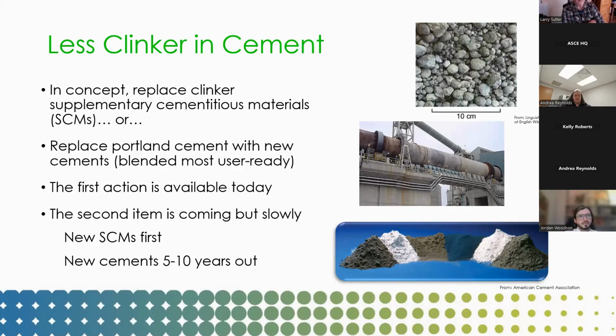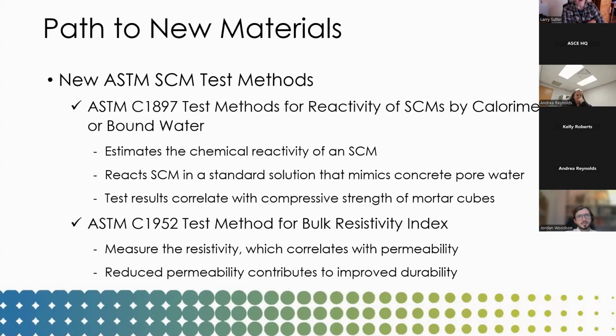Next slide. So how do we get there? Well, the first thing we got to do is look at new tests that are going to help provide us information we need. And so we do have a couple new tests. We've developed C1897 for measuring the reactivity of SCMs by calorimetry or bound water. And this is a completely new approach to estimating the strength contribution of an SCM. And the testing correlates quite well with compressive strength of test mortars.